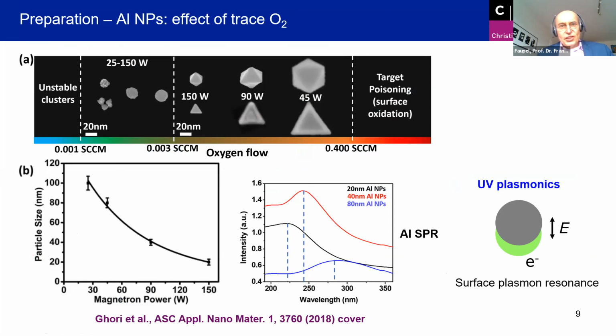Here's another example of such nanoparticles. In this case, these are aluminum nanoparticles, which we produce by such a cluster source, and they are very interesting for UV plasmonics. Most of you probably know that you have collective excitations of the conduction electrons in such nanoparticles, surface plasmon resonances, and usually you explore such surface plasmon resonances in the visible range. Here we focus on UV plasmonics, and we can tailor the resonance frequency over a wide range by tailoring our nanoparticles. A typical application is absorbers, broadband absorbers for ultraviolet applications, for instance.